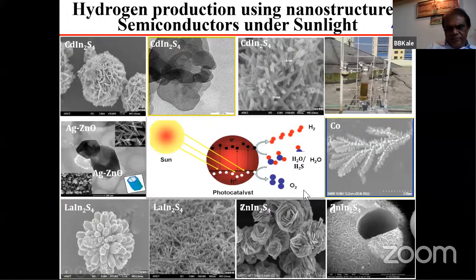Then the lanthanum indium sulfide series and the zinc indium sulfide series. In the zinc indium sulfide series you have hollow nanostructures. Then we have a rose-like structure, with very thin petals. These are important because the surface area is increased drastically using such structures. So the morphology of nanostructure is also important for any kind of application, and I would like to convey this.